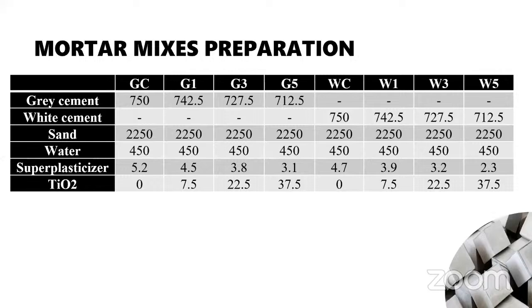I hope you heard the part where I was mentioning the percentages of titanium dioxide. So we used 1%, 3%, and 5% by mass of cement materials in our mortar mix to obtain a medium strength concrete with a water to cement ratio around 0.6. Next slide, please.